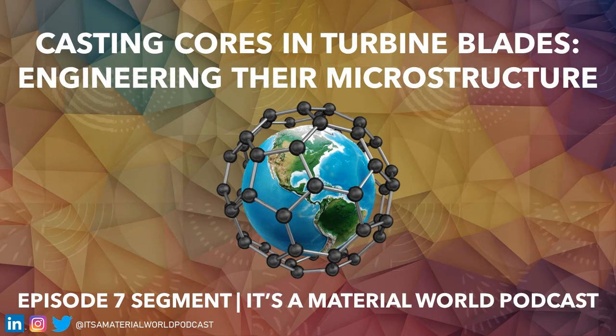To make the cooling passages in that stage 1 turbine blade, you would need a casting core that had a silicate type of composition. What's interesting about these casting cores is that unlike other ceramics, which you think of as strong, you want strength but not too strong. You want to be able to get it out at the end of the process of casting your metal. And to do that, you have to use an autoclave in a caustic environment and pressure, basically leaching this ceramic out of the metal at the end of the day. So if it's a really strong ceramic, you won't get it out, and then you won't have your air passage. If it's too weak, it won't survive the casting process.